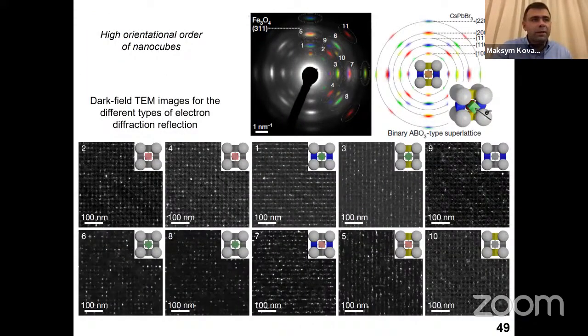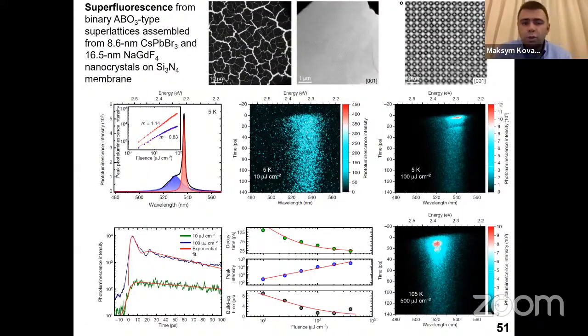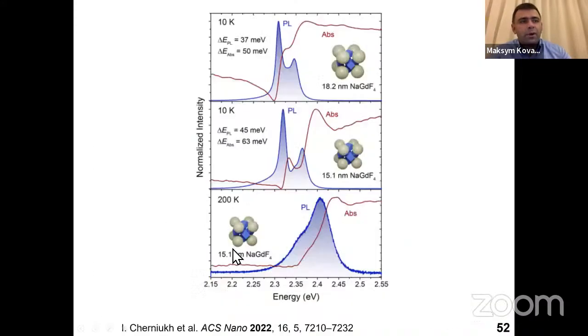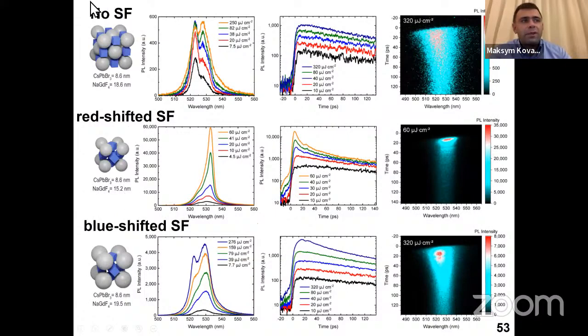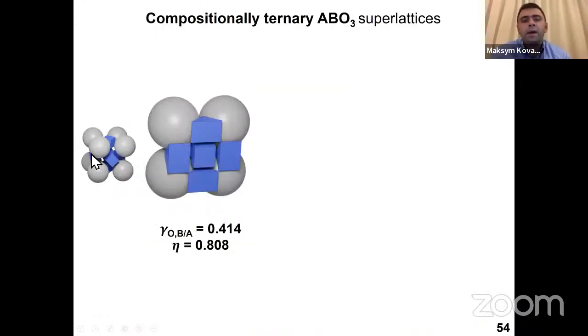And so just for the last few minutes, I will show you that indeed these structures do show superfluorescence as well. What is more interesting is that if you compare different kinds of superlattices, you start seeing correlation between the structure and the superfluorescence that you observe. For example, in one case, you even see the blue shifted superfluorescence. In another case, you see the superfluorescence threshold for the appearance as a function of the dielectric sphere diameter. And in another case, you do not observe superfluorescence because the volume fraction of perovskite particles per volume is much smaller than in such type of a superlattice. So you start correlating your superfluorescent property with your structure.